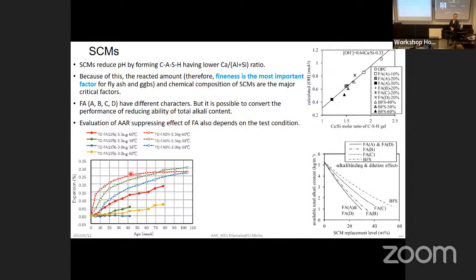I just read and I'm wondering how much we can use glass powder, really thin, like the size of cement or even thinner, to partially replace the cement. Because glass is an amorphous material, in some way there will be some kind of reaction with the calcium hydroxide. Yes, like silica fume or fly ash. We will have some kind of pozzolanic reaction. But the point is we are putting alkalis inside. Because they are not so rich in sodium and potassium, alkali metals, that can reduce the alkali-silica reaction by reducing pH.